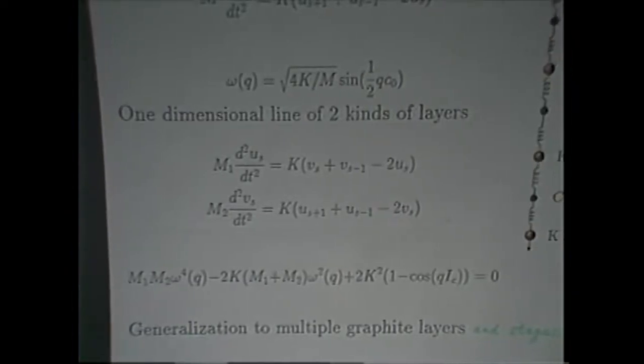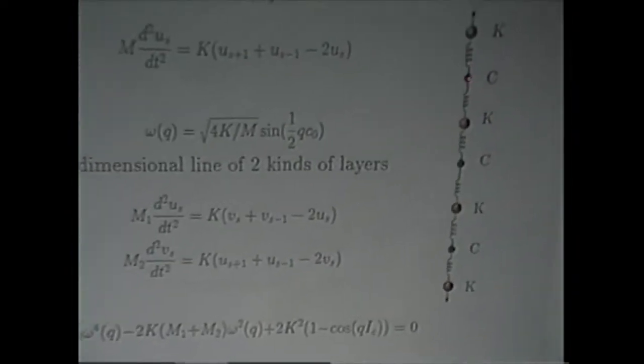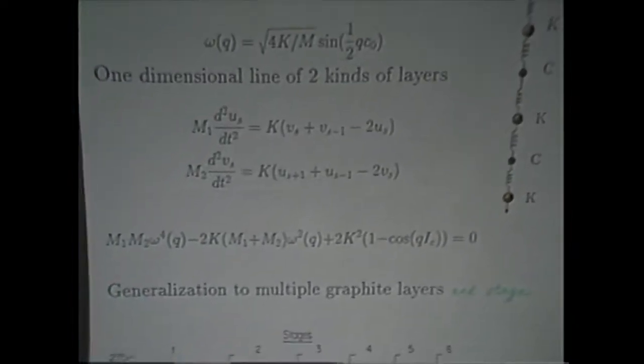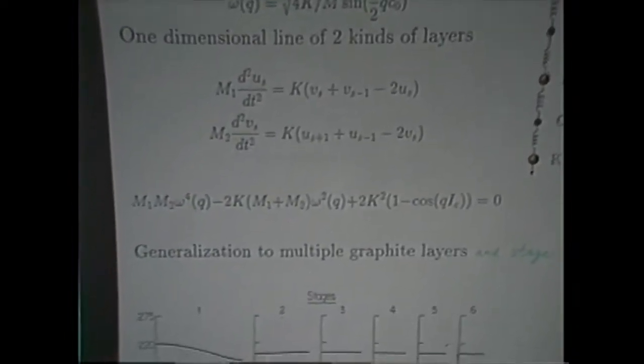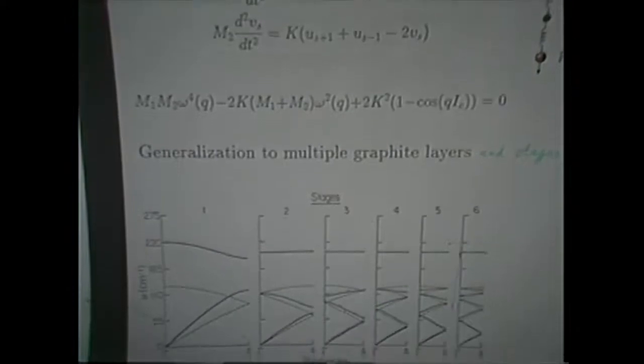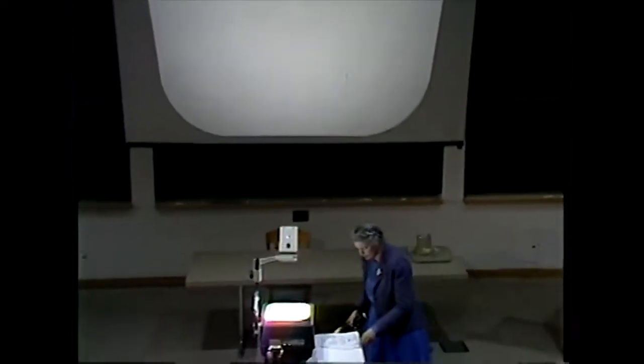Well, an intercalation compound is really two different species, intercalant and graphite layers, each layer represented by one ball. And when you use that model, you get very nice phonon dispersion relations, and just fitting these, you get the constants for the forces. So phonon dispersion relations provided a nice set of examples for the solid-state course. Now, how do we understand the experiments